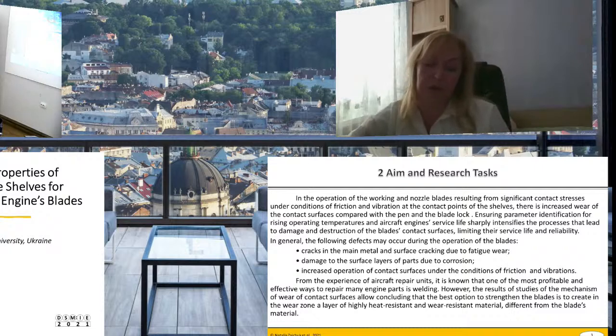From the experience of aircraft repair units, it is known that one of the most profitable and effective ways to repair many engine parts is building up. However, the results of studies of the mechanism of wear of the contact surface allow the conclusion that the best option to strengthen the blades is to create in the wear zone a layer of highly heat-resistant and wear-resistant material different from the blade material.